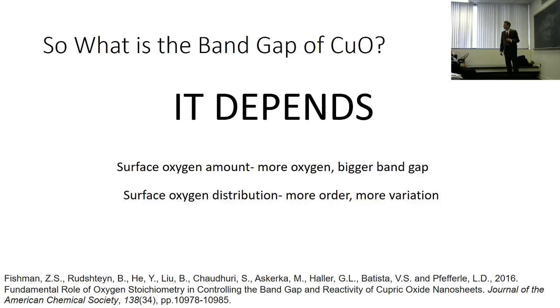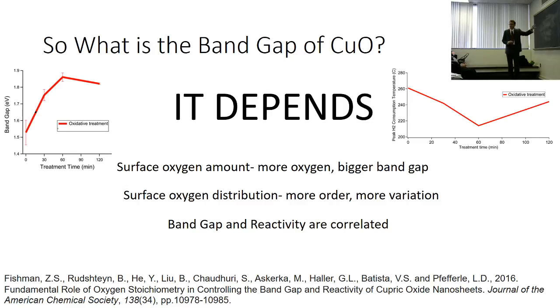And the third takeaway I want you to get from this is that in this system, copper oxide nanosheets, the band gap and the reactivity were correlated. When you go up in band gap, you went higher in reactivity, so lower temperature in reacting with the hydrogen. Does this solve all the problems in the literature? No, I'm not saying that this is why everything is kooky. I'm saying that this might be one reason.